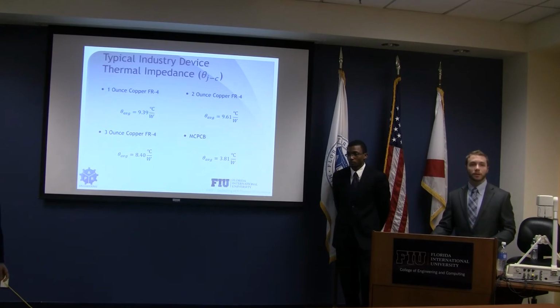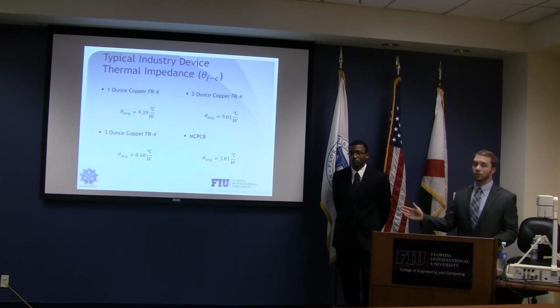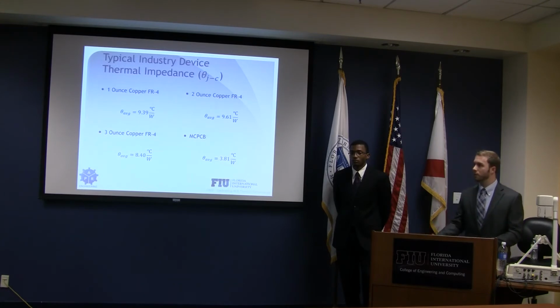For comparison, these are typical industry standards for boards, and as you can see, both of our devices perform better than typical FR4 boards with different weights of copper, which are 1 ounce, 2 ounce, and 3 ounce, in ounces per square foot of board. And then it came close to an MCPCB, which is solely a metal board, which says that our device actually performed very well.